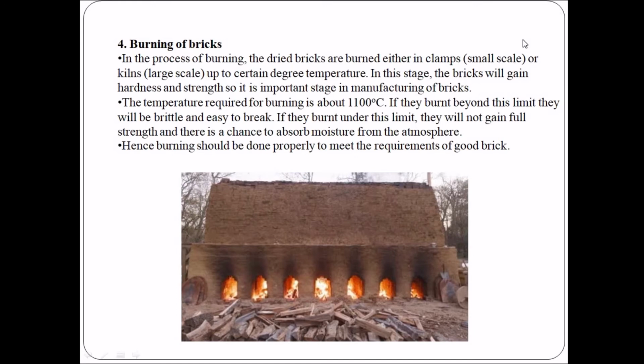The next operation is the burning of bricks. In the process of burning, the dried bricks are burned either in clamps or in kilns up to certain degree of temperature, and in this stage the bricks will gain hardness and strength. So the temperature required for burning is about 1100 degrees Celsius. If they burn beyond this limit, they will be brittle and it will be easy to break. Hence, the burning should be done properly to meet the requirements of good brick.